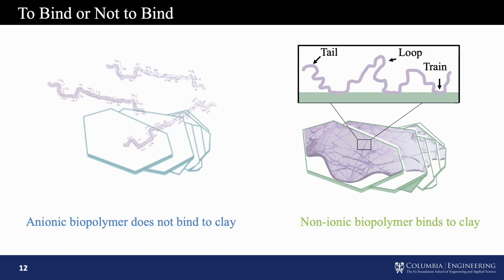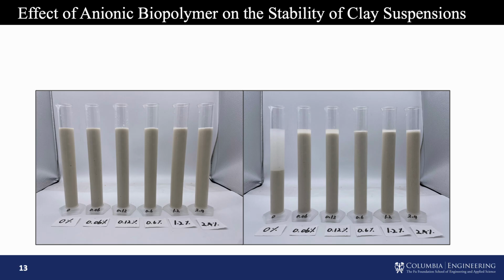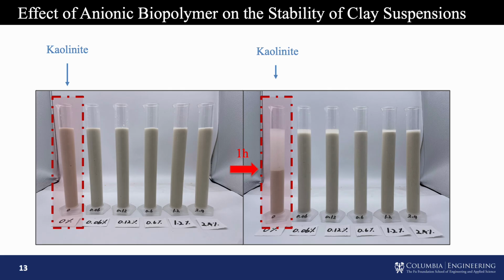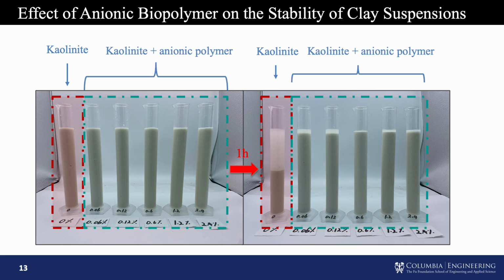And we have these two types of polymers, right? We have the polymer which binds to clay, which is a non-ionic biopolymer, and another polymer which does not bind to clay, which is an anionic biopolymer. So let's see how this anionic, or non-binding, biopolymer affects the suspension stability. Clay naturally flocculates and settles because of van der Waals forces and hydrophobic interaction between clay particles. So if you put them in a tube for 1 hour, it will show very strong settling behavior. But if you add a very small amount of biopolymer, this is the sodium alginate,